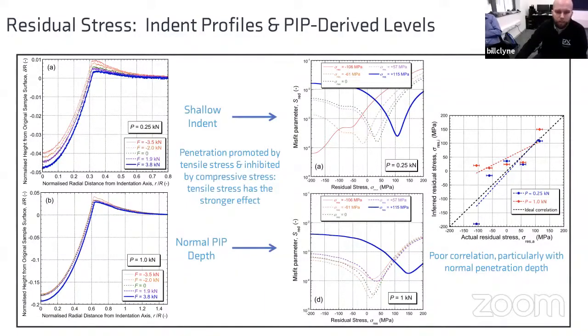So what we can then do is take those indents. We know the plasticity parameters because we can take that from our indentation experiment performed on a sample with no residual stress. So we put those into our FE model, and we then vary the residual stress, and we can then calculate the misfit parameter for each of those values of residual stress. And what we can see here is that we do get a minimum and therefore a best fit for each different value. And you can see that each of these does have a minimum rising on either side.